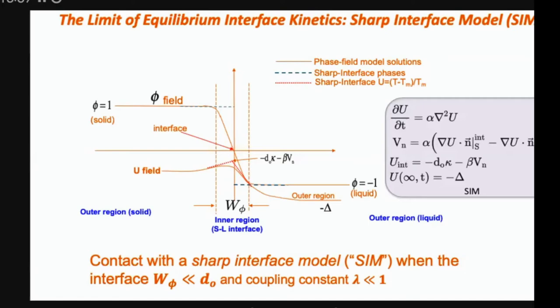And so you can then tune the parameters of the model so that effectively simulating the model is equivalent to simulating a sharp interface model, which essentially assumes the interfaces are sharp compared to every other structure in the system. And your process is being driven by diffusion and two boundary conditions, one telling you how the velocity moves locally based on thermal gradients across it, and one that tells you that the interface has to always be at some kind of equilibrium, corrected only by curvature effects. So this is an equilibrium sharp interface model, and most phase field models kind of operate in that regime.